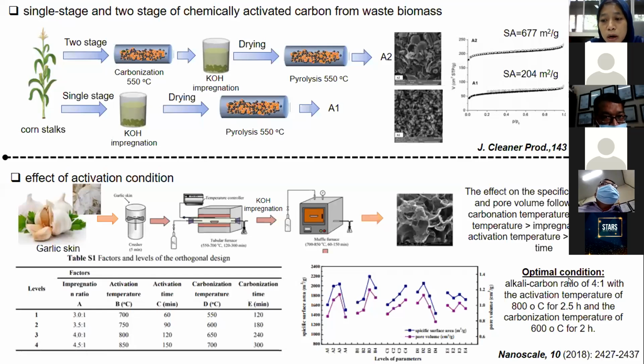And this is the optimal condition to synthesize the activated carbon from garlic skin. And in general, the influence level of preparation conditions on the pore structure of carbon followed this order: the carbonization temperature gives the highest effect, followed by the activation temperature, the impregnation ratio, the activation time, and the last is the carbonization time.